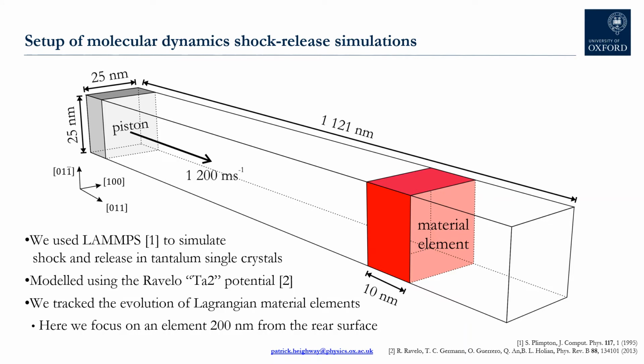The central focus of the simulations was to track the evolution of a set of Lagrangian material elements as they undergo shock and subsequent release, monitoring their temperature throughout, and to see whether their behaviour could be understood with reference to their strain state, stress state, defect state, and so on. I'll be focusing on the results for a particular element situated just 0.2 microns from the crystal's rear surface.